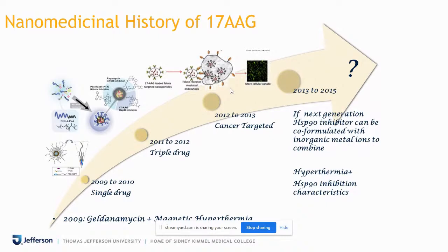In 2009, a paper was published where a researcher from Japan used geldanamycin and magnetic hyperthermia in synergy for the treatment of cancer. Now I'm introducing a term called magnetic hyperthermia. What it means is that when you give magnetic nanoparticles like Fe3O4 and expose them to an alternating magnetic field, such as in an instrument like MRI, where you are exposing your body to an alternating magnetic field, similarly, if you have a coil which can create an alternating magnetic field and you put magnetic nanoparticles in between, they have a tendency to resonate and cause localized heating.